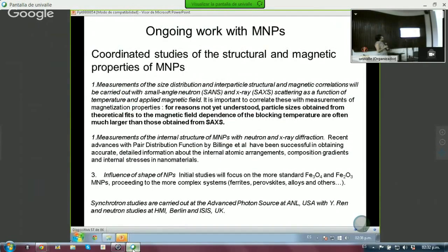magnetic nanoparticles. Okay, so when you make such a synthesis, you go to your lab and you use TEM or STM or something like that to measure the size of these nanoparticles. But there are other techniques, and there you have to take a specific amount of sample and put it on a grid. And when you're dropping these liquids, since they are sitting in a cavity, in a way they are being slightly confined.